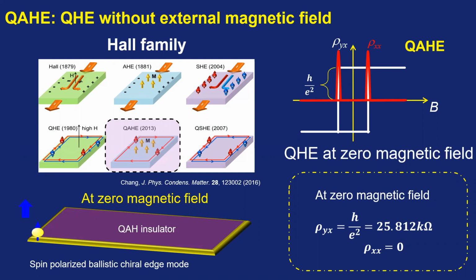So today in my talk, I will focus on the realization of the last member of the Hall family, called the quantum anomalous Hall effect, in the magnetically doped topological insulator thin film. In the quantum anomalous Hall effect at 0 magnetic field, the edge state depends on the magnetization of the sample. When the magnetization is up, the edge goes this way. When the magnetization is down, the edge goes the opposite way. So the chirality of the edge current in the quantum anomalous Hall effect depends on the magnetization of the sample.